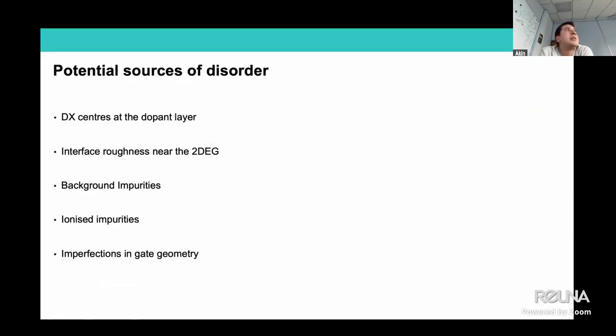So disorder in these devices can come from a very large range of things, and they can happen in the fabrication process, like damages to gates or structure, or even the wafer itself. There could be DX centers in the dopant layer, so deep traps. There could be roughness in the interface of the junction. There could be background impurities, ionized impurities from the dopants, which we usually assume to be homogeneous at the dopant layer that I discussed before. But there could be inhomogeneities there, and they would have different effects.